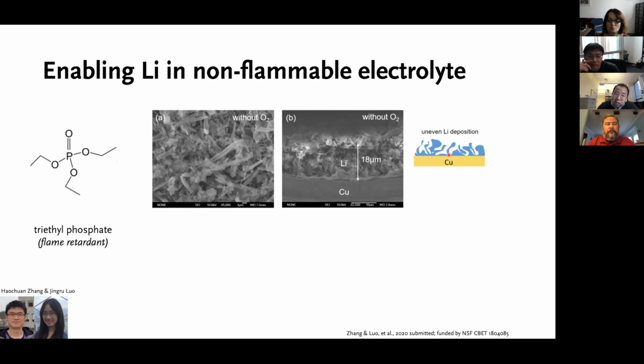Also, you will notice that there will be very narrow necks at this contact. And when you try to oxidize this, that is during the discharge, for instance, lithium here could be first oxidized. What that does is cut the connection between the rest of the lithium and the current collector. Hence this becomes loose lithium, dead lithium, that will float away. It poses a number of problems. First, you are no longer able to access the capacity stored in this lithium. And more importantly, over time, it deposits and could short the circuit.